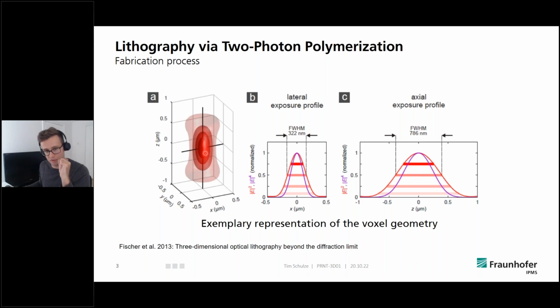the process for the polymerization here is based on two-photon absorption, and two-photon absorption is a nonlinear optical process that is proportional to the intensity squared. For this reason, the resolution of this process is way higher than, for instance, normal UV irradiance with a UV laser, as used with stereolithography.